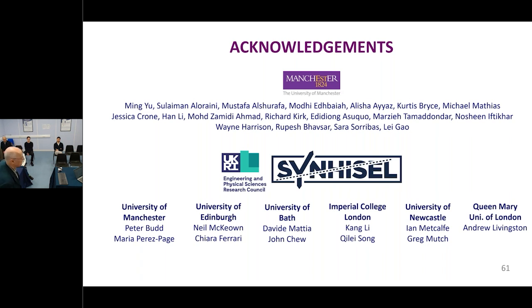Okay, well, the commercial application was a sensor application rather than a separation application. The sensor was actually devised by 3M, and they realized that PIM1 or a PIM was the material they needed, because what they wanted was something which would absorb like an activated carbon and be processed into thin film, which is exactly what we wanted. So they developed the sensor, but they licensed the PIM technology from us effectively. There are a number of papers out there. Later I can send you references if necessary, but if you Google Neil Rakow, N-E-I-L R-A-K-O-W, you should be able to track some down.